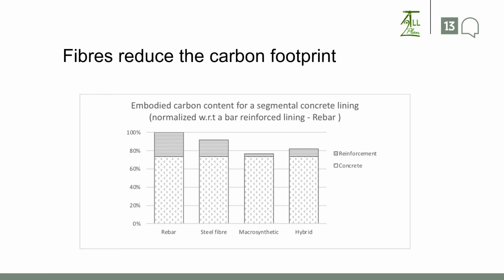So this is a typical segmentally lined tunnel. It's a metro tunnel, 6.5 meter diameter. If you have a typical bar reinforcement, you can see how using steel fibre will reduce that significantly, maybe 10%. Macrosynthetic, if you can use that, will reduce it even more. And the hybrid here is a combination of the macrosynthetic with perhaps a cage just underneath the ram shoes, which is also quite a good option, very effective structurally.